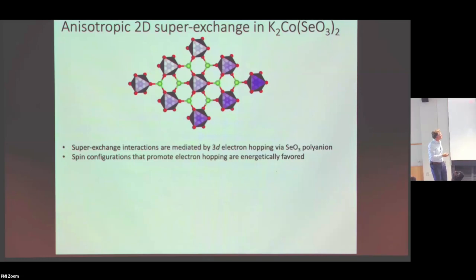The interaction is not a dipole interaction. This is very, very important to remember. It is a super exchange interaction. It has to do with d electrons which are hopping between these cobalt atoms, and they're passing through this polyanion site. But because those are now spin-orbital degrees of freedom, they have at least the possibility to be anisotropic, and it turns out that they do have a strong Ising component.